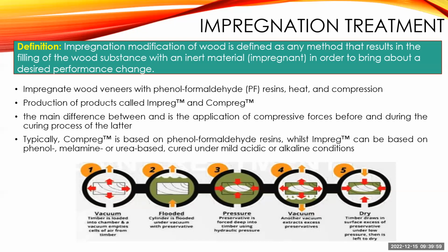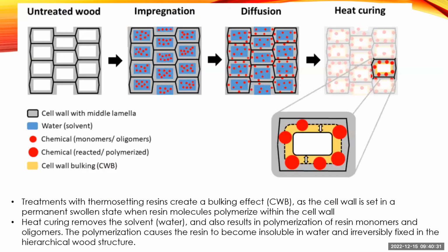Here is the schematic figure of the impregnation treatment. The timber will be loaded into the chamber, and then vacuum is applied to empty the cells of air from the timber. Then the cylinder is flooded with resin, and we apply pressure. After that we apply another vacuum to extract the excess resin, and then let the timber dry. This is the very common resin treatment method in industry.